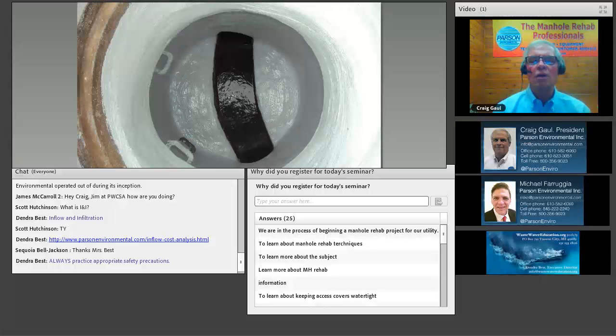So speaking of MIC corrosion, Mike had mentioned earlier, we do have an additive for that we can put with either our Portland cement product, which is the MH Liner, or the calcium aluminate product, which is called CA Liner 100. The dosage is about 6 ounces per bag. And again, when it's applied, it looks the same as it looked when there was just water. But what this will do is break the chain of events so that the bugs will not be able to inhabit the walls, and therefore will not be around when hydrogen sulfide is present, and obviously that will not allow the hydrogen sulfide to be turned into sulfuric acid.